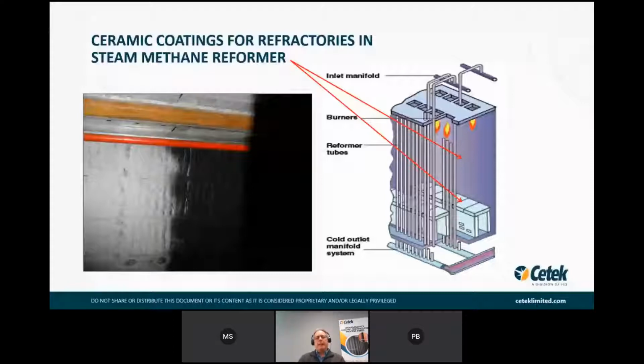And I would also say in parallel to not only the CO2 and the NOx, there's another environmental win, which is the encapsulation characteristics that you get from ceramic coating. On ceramic fiber, which we all know at some point will become oxidized, will tend to dust, and that dusting crystallization will end up going downstream into your convection section, right? It's not a good situation, certainly in the long term. So if you apply a ceramic coating to that surface, it will stop that crystallization, which of course is one of the root causes for that fouling.